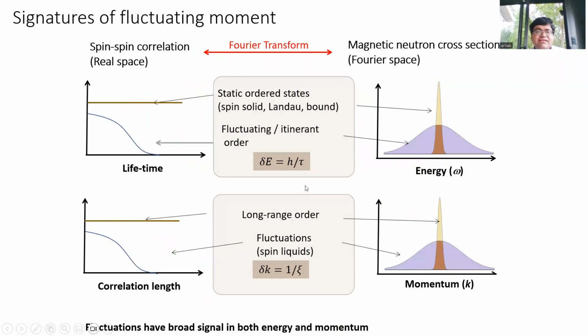That can happen if you have very strong spin fluctuations. And if you have strong spin fluctuations, what you would see are pretty broad features in energy-momentum space. That comes from the fact that when you have spinons and a high degree of fluctuations, the lifetime of the spinons is small. If you have a small lifetime in real space, in energy space it means that your energy dispersions will be pretty broad, because it's the Fourier inverse.